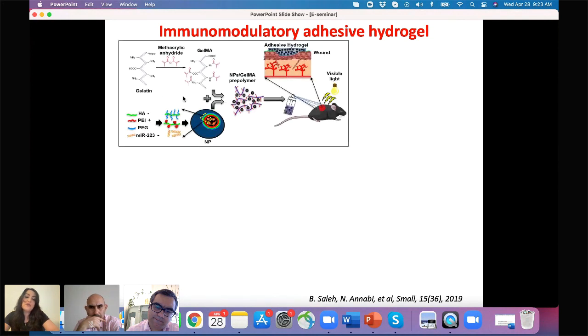In addition to hemostatic and adhesive biomaterials, another area that we work in the lab is to form this bioadhesive with immunomodulation characteristics. So to do this, we use a nanoparticle platform which is loaded with miRNA. Once we form these nanoparticles, the base of the nanoparticles is hyaluronic acid. So once we form these hyaluronic acid-based nanoparticles loaded with miRNA, we can combine them with any kind of photocurable bioadhesive. And by mixing them and applying them on the wound, we can form an adhesive hydrogel that can also release this miRNA over time to control inflammation on the wound site.